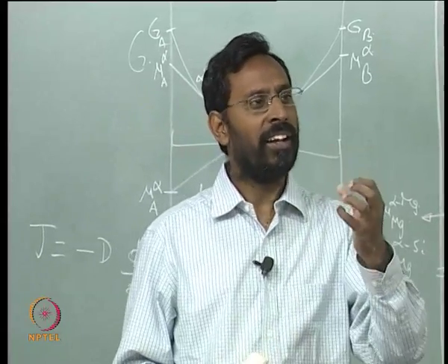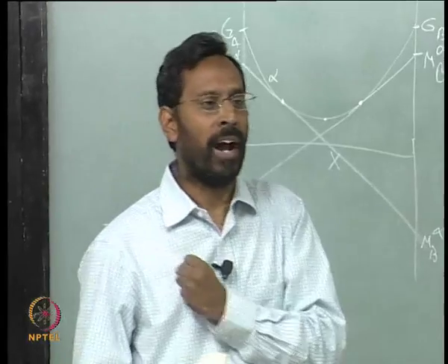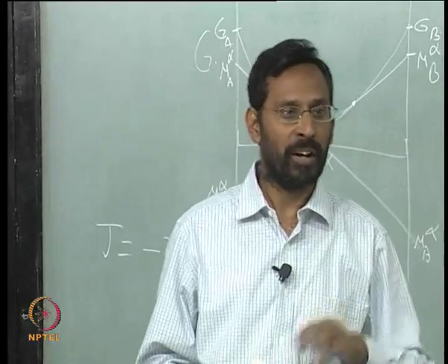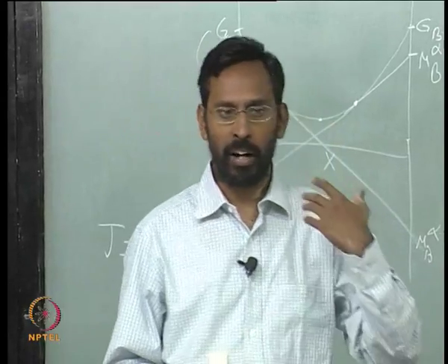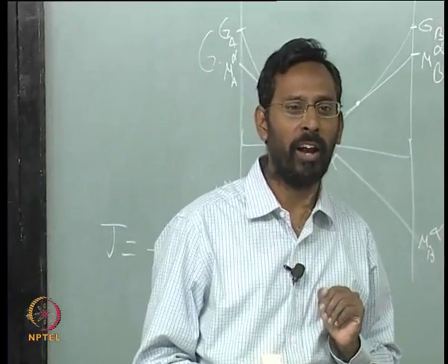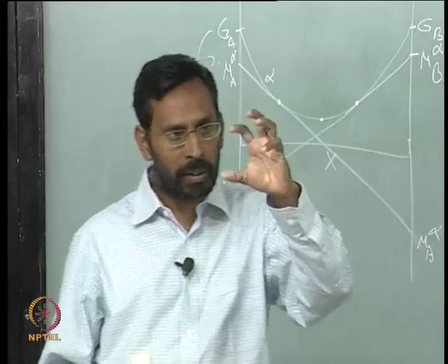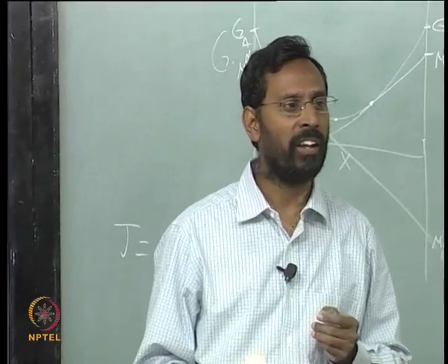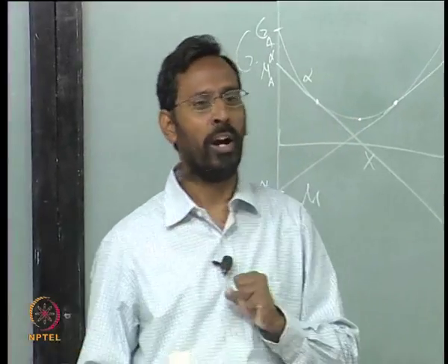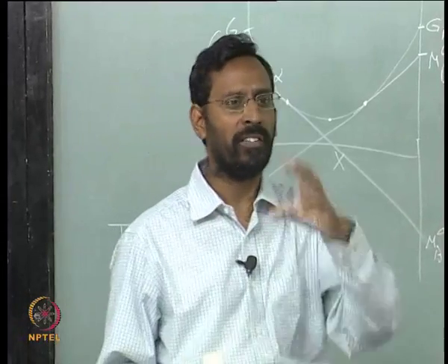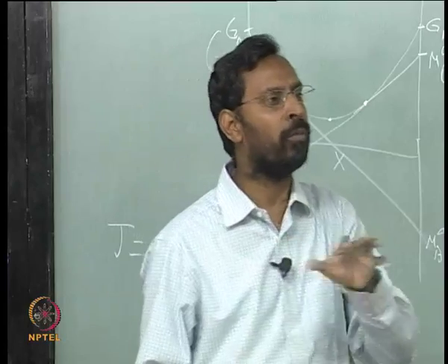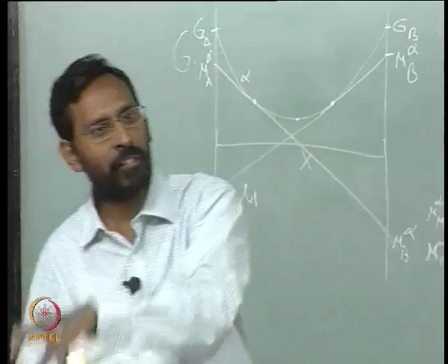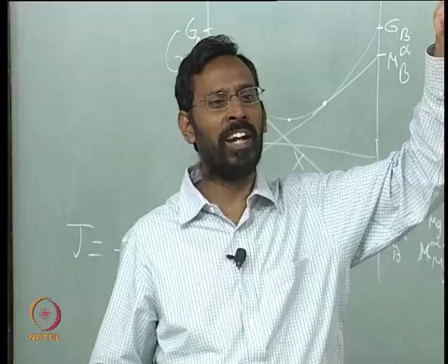The reason is silicon, the moment it is present, it locks up the carbon and reduces the activity of carbon atoms. There are certain elements which have this tendency. For example, compound forming elements, carbide forming elements, the moment I add them to an alloy steel, all these carbide forming elements will lock up the carbon. Let us say I add chromium, vanadium, titanium to a cast iron or a steel, you see that all these lock up the carbon and reduce the activity of carbon. Once the carbon forms a compound, the carbon atoms cannot move further because they are strongly bonded with some other element. So, once the activity of carbon comes down, now you have to actually see the activity gradient and not the concentration gradient.